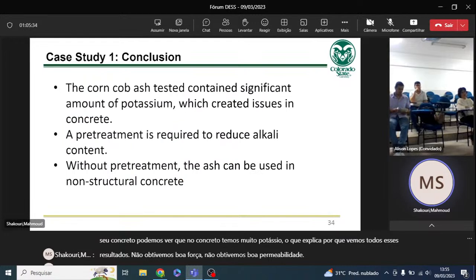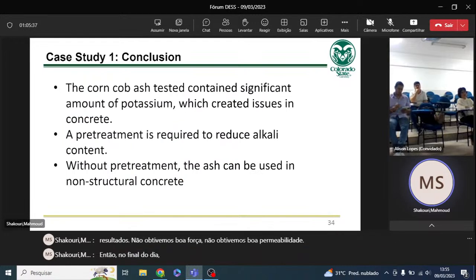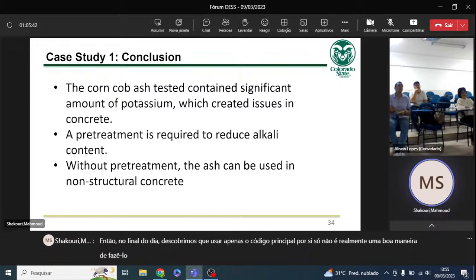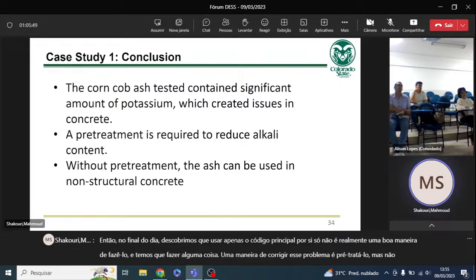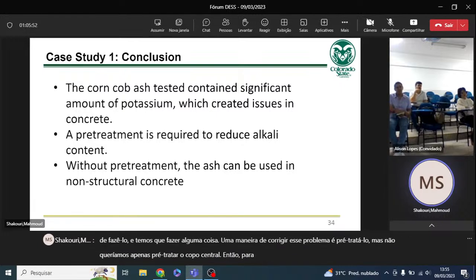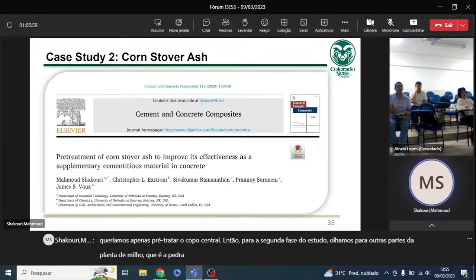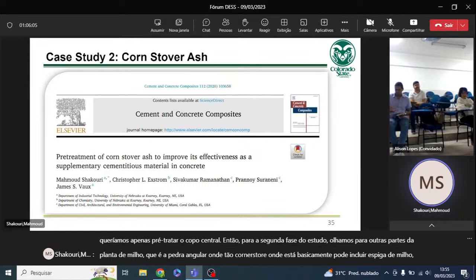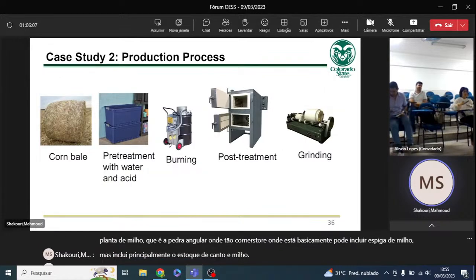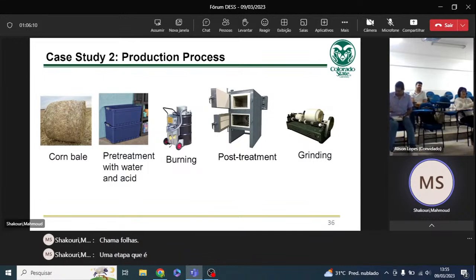So at the end of the day, we found out using just the corn cob by itself is not really a good way to do it. We have to do something. One way to fix this problem is to pre-treat it. But we didn't want to just pre-treat the corn cob. So for the second phase of the study, we look at other parts of the corn plant, which is the corn stover. So corn stover can include corn cob, but it mostly includes the corn stalk and corn leaves. One step that is added to this part is the pre-treatment.